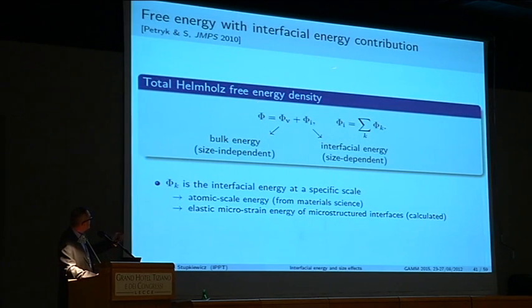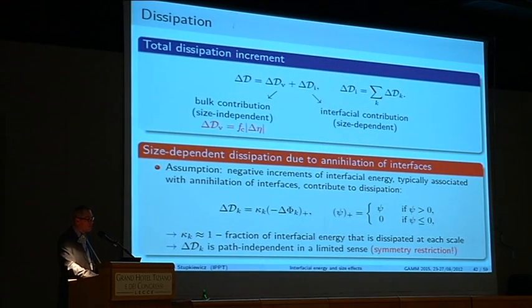So what we do, we just consider our free energy to be composed of the bulk size independent contribution. We know how to do this, as in our models, or the traditional models, and then we also add the interfacial energy, which is a sum of interfacial energy at individual scales that we consider. And then, in particular, we have these two types of contributions, the atomic scale energy and the elastic microstrain energy, which we predict using our micromechanical schemes. We do a similar thing for the dissipation. So we consider bulk dissipation, where we put all that we don't know and assume this one is rate independent and size independent. And then we have also interfacial dissipation related to the individual levels of microstructure.